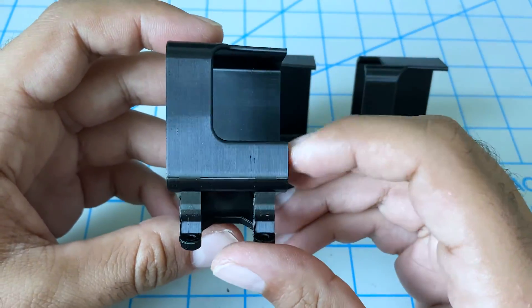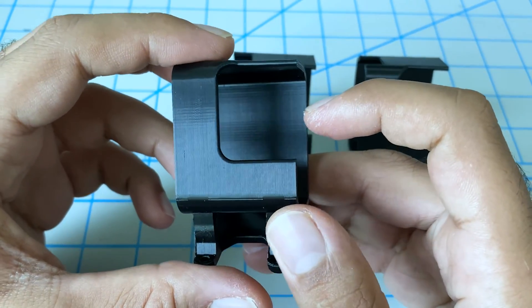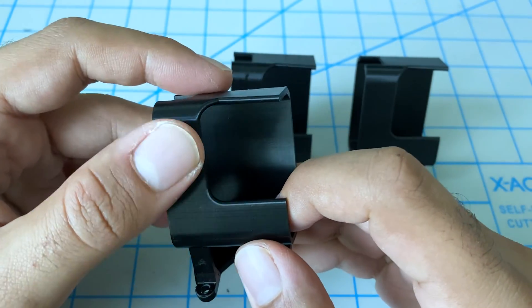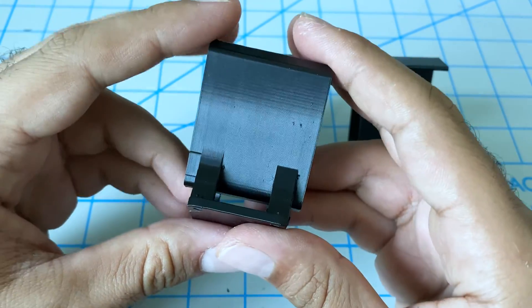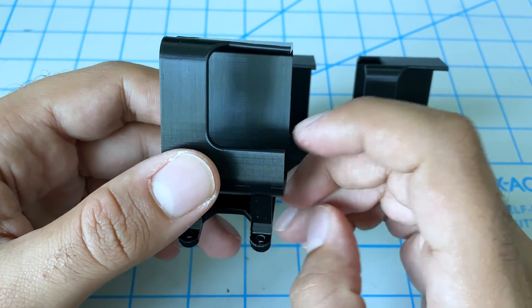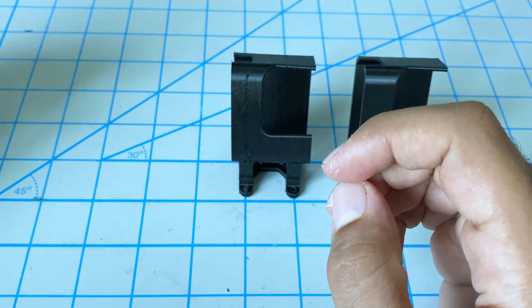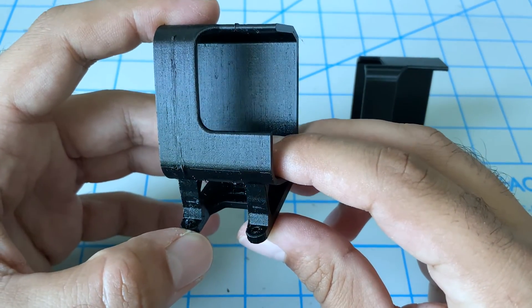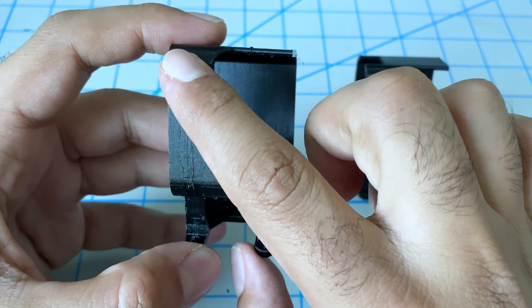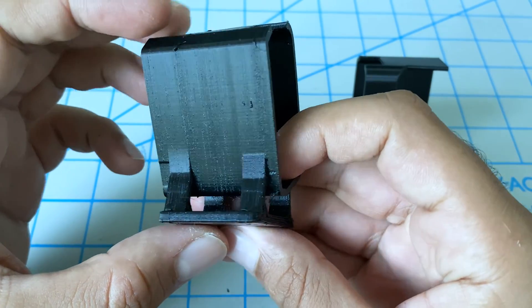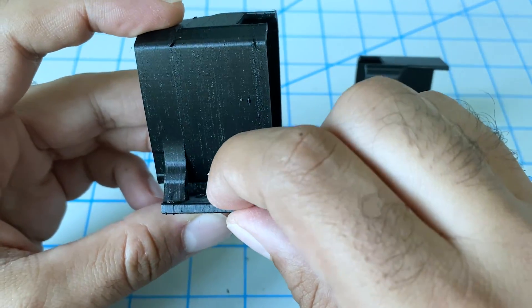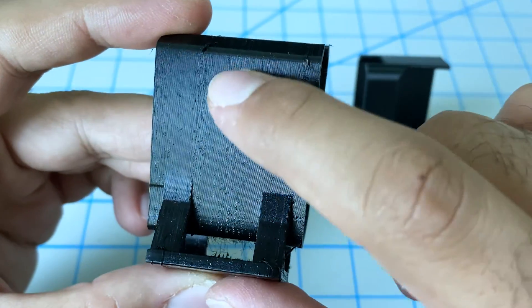Here's the first GoPro mount that we printed when the filament was brand new. We can see minimal stringing, very smooth finish, looking actually quite nice. And of course this is a six or seven hour print. So while we printed two of these, the filament had a lot of chance to absorb moisture. And this is what we got. So we can see that there's a lot of stringing. The texture of the print looks terrible. And even what you see here is after we cleaned it up a little bit. But just down here you can see how much stringing we got, how bad and rough the texture is.